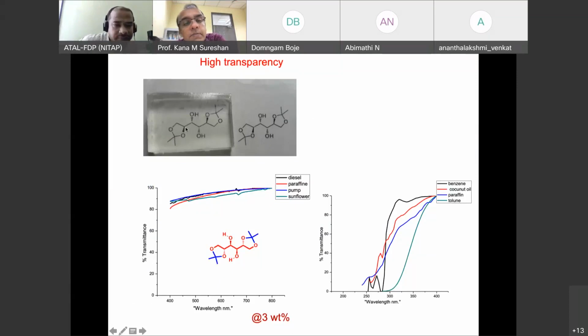That means the transmittance or transparency of this material is high. This is the transmittance data in the visible region of the spectrum. You can see from 400 to 800, about 90% of the light is transmitted. And in the UV region from 200 to 400, you can see it is completely absorbed. So basically this is a UV filter. If you pass light through this material, it will filter out UV by absorbing and give us the good, safe light, which is the visible light.